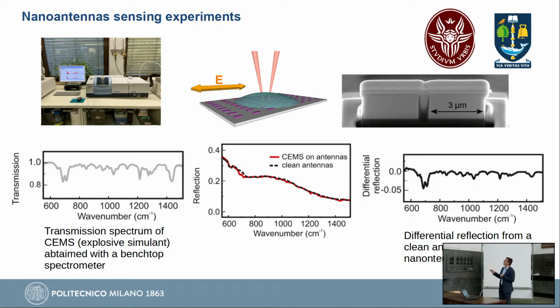So we fabricated an array of antennas. We covered it with this substance. And we actually took, in reflection geometry, the differential reflection between the chip with the explosive simulant and without. So these two curves looked pretty much similar. But if you take the difference, you recover a spectrum where, for example, here, around 700 inverse centimeters, you see exactly the same peak.